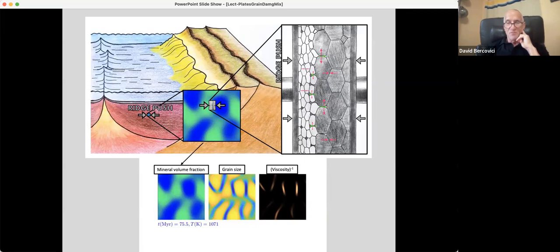The blue bands are small grains here in the, if I can get my arrow to cooperate, okay. In the region, the yellow bands are just high grain size, and the blue is small grain size, and where the grain size is small is where viscosity is low. Okay, and so you're seeing where the copper colored bands are on the far right. These are weak zones, but they're weak and oriented in the vertical direction because mixing is in the horizontal direction on boundaries between the olivine and pyroxene that are vertical. So you wind up getting a strong vertical banding, vertical bands that are weak.